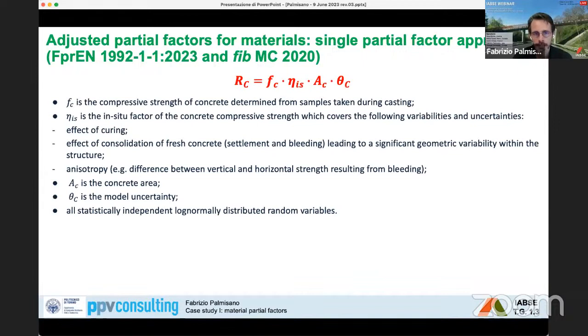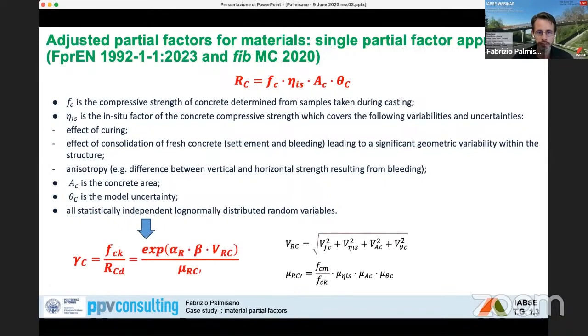In this, the basic assumption is that the general variable of the concrete strength, RC, is a product of the FC, the compressive strength of concrete determined from samples taken during casting, the in situ factor, and the geometrical and model uncertainties. All these variables are assumed to be statistically independent and log-normally distributed. So by making this assumption, it is possible to calculate the gamma factor for concrete as the ratio between FCK and the design or assessment value of RC.